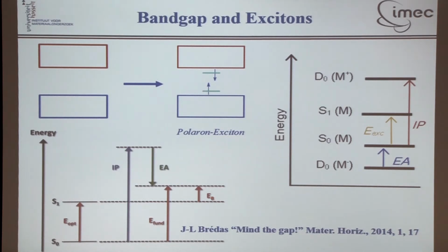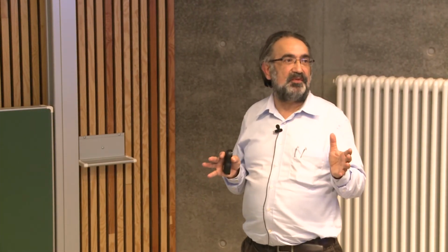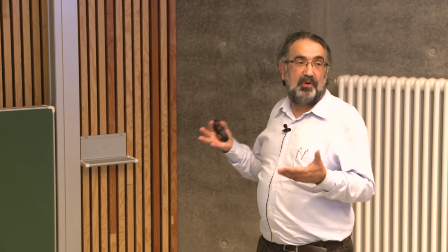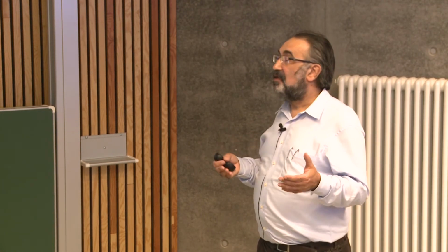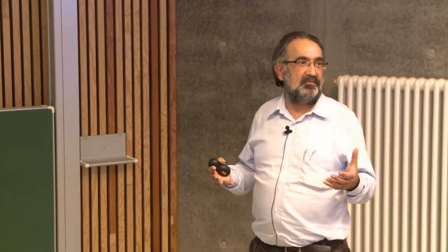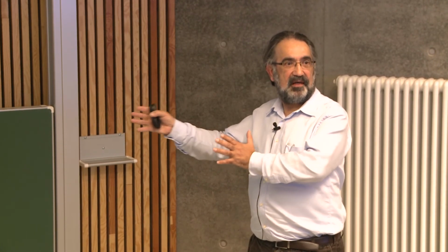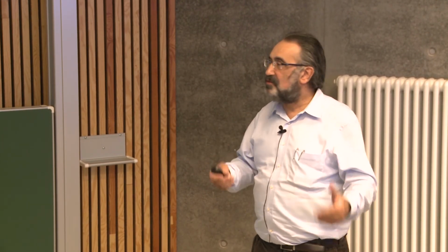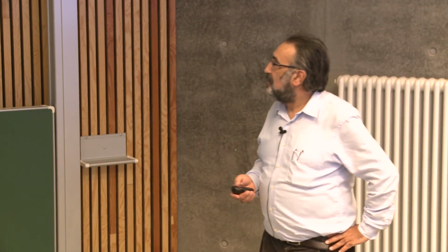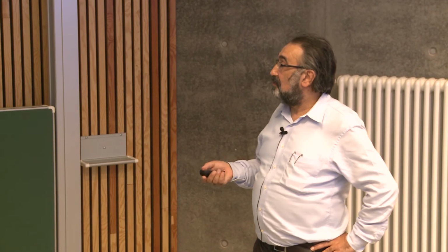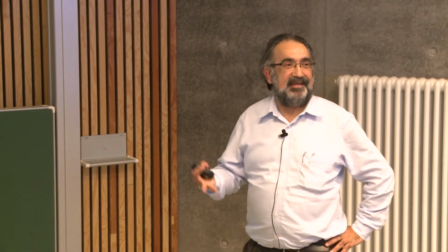Now, how large is that? What's the error that you make? Depending on the source, somewhere between 0.1, 0.2, 0.3 eV. The largest values you can find, because there's always an estimate, are something like 0.3. This is an important point to make. Actually, you do a kind of approximation. But quite often this works because you compare different materials. So it's always in a relative context that you use this concept of band gap. So independent of this criticism, it works.